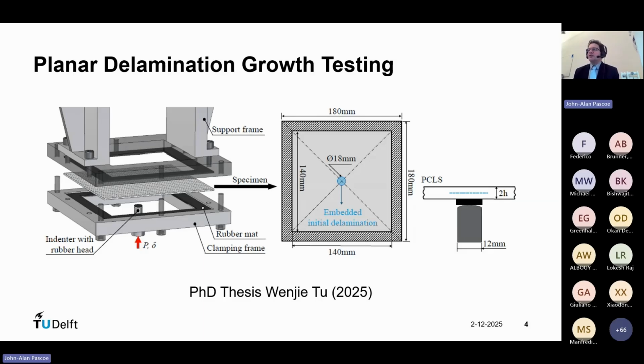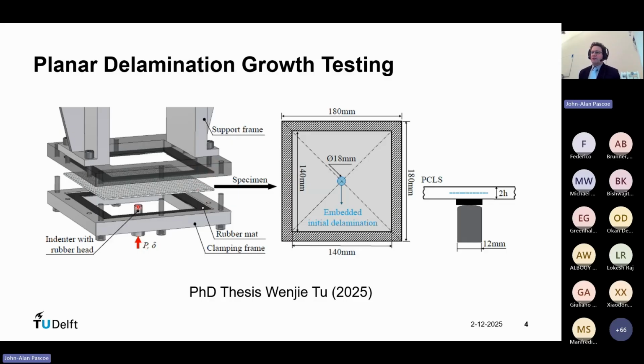He developed this planar delamination growth testing setup. So you have, let me see if I can activate the laser pointer. Yeah, so we have a square specimen that's clamped with rubber between these two metal supports. And then we have out of plane an indenter with a rubber head pushing onto the bottom of the specimen, pushing it up out of plane. And then in the middle, we have a Teflon insert to initiate the delamination.